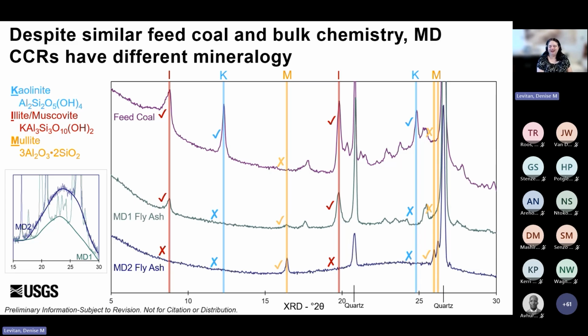So what this is showing, XRD measures, it shoots X-rays at the mineral sample, and then depending on what crystals, what minerals are present, the X-ray beam is diffracted at different angles, and you get a set of peaks, and each mineral has kind of a diagnostic set of peaks, so you can identify from all of the peaks present what minerals are likely present. Not down to a very small degree, like we actually can't see if there are any rare earth element minerals because the fractions of those would be too small since we're looking at those ppm levels. But for major mineral phases, you can see based on these peaks what's there. So I'm going to go over a few of these minerals just to look at how that changes from the feed coal to the ashes.